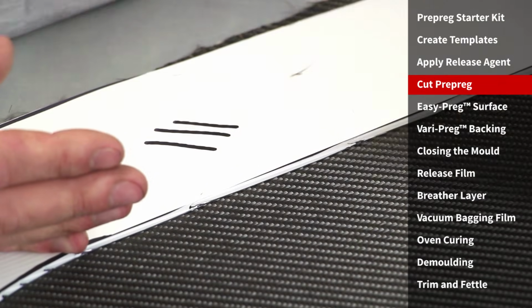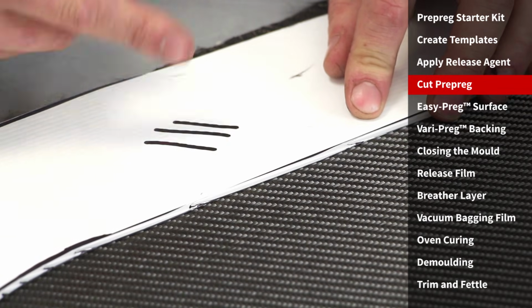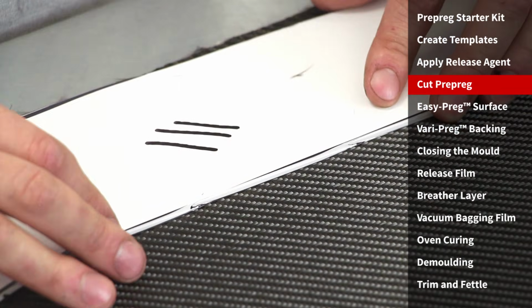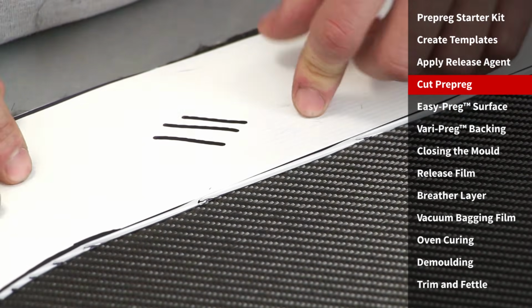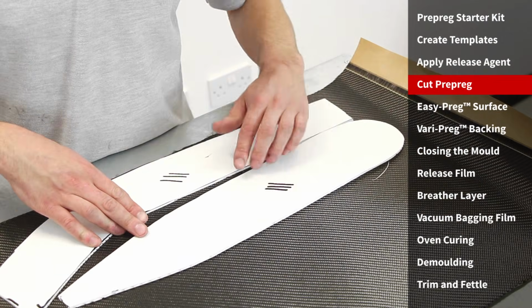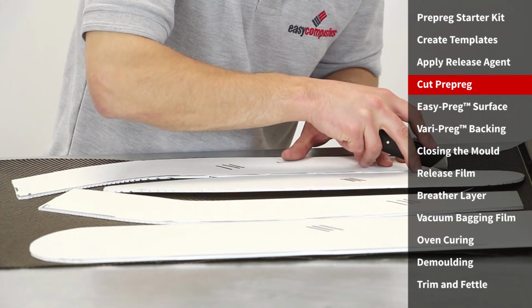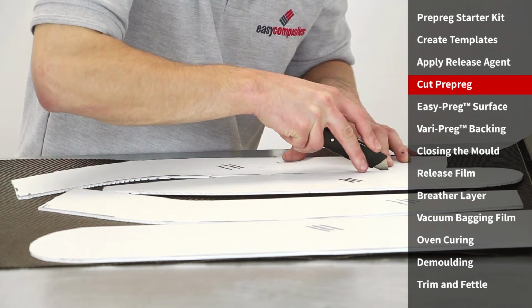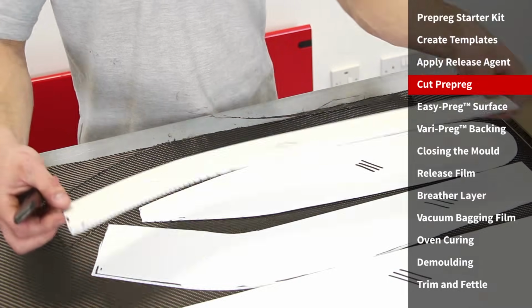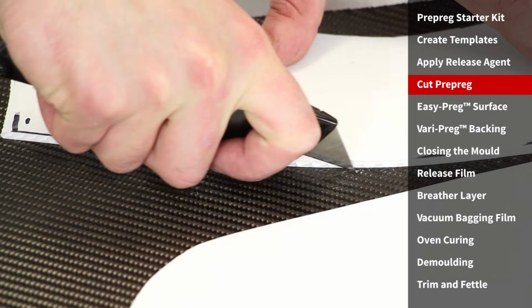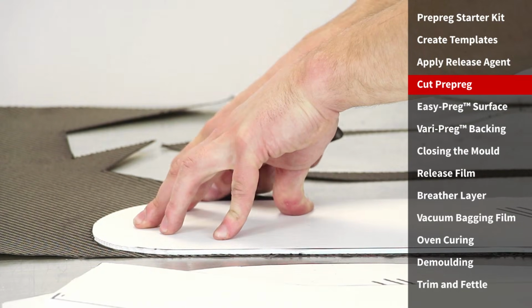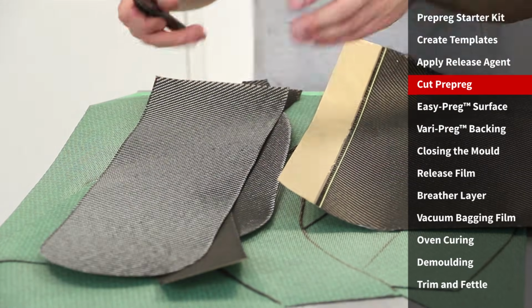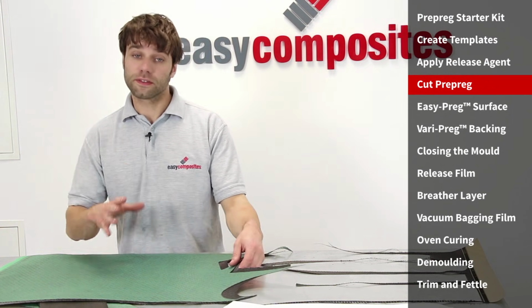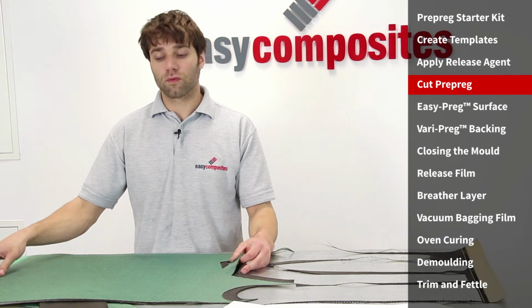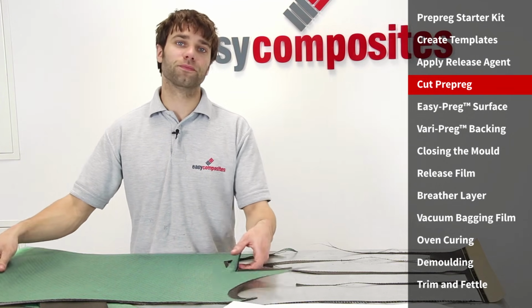So we're looking to ensure that our weave alignment is absolutely perfect on all of these parts. With the twill fabric, you get quite a distinct line running in the diagonal across at 45 degrees to the weave. And these lines here, we're looking to align with the lines that we can see on the surface of the material. So we'll just be taking the templates and making sure at every stage that that line carries through from the ones that we've marked. The excess material, if it's not going to be used immediately, can be rolled back up, put into a sealed bag and refrozen.